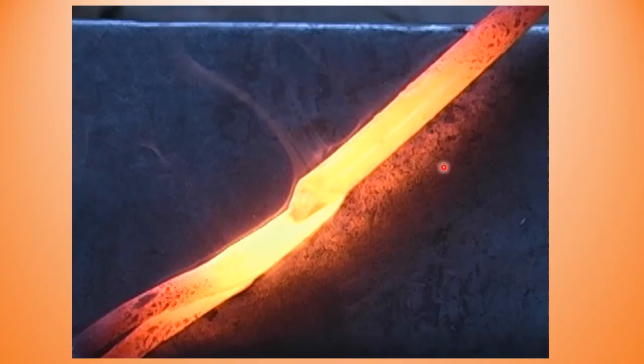So here is a color photo of two pieces heated to that high end of the welding temperature range and fitted together on the anvil. The thing that I want you to notice is that this welding temperature has a wet look to it. That is a clue that it's welding temperature. The parts on the edges here that are not welding temperature have a dry crusty look. So position the two pieces on the anvil while you still have this color.